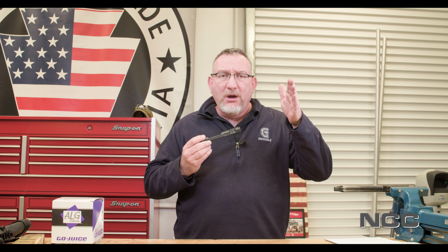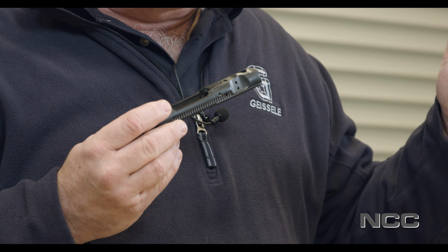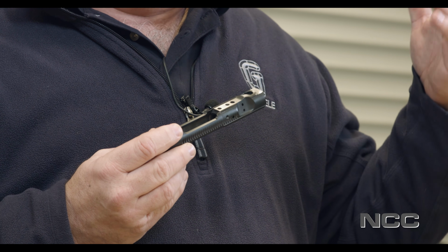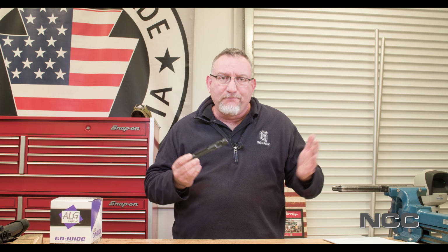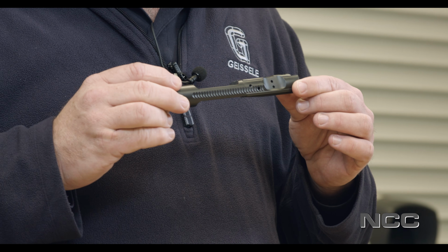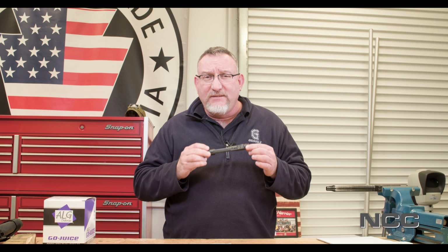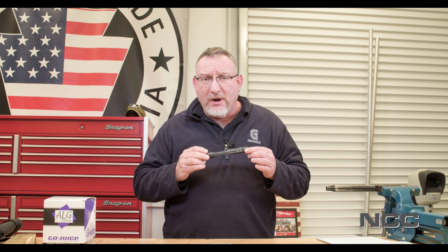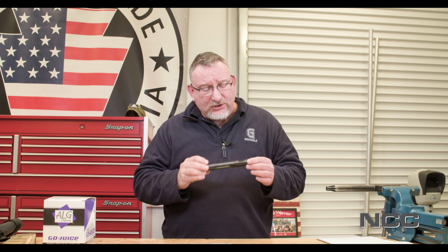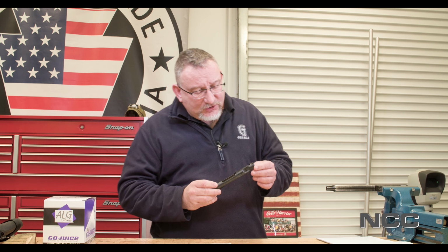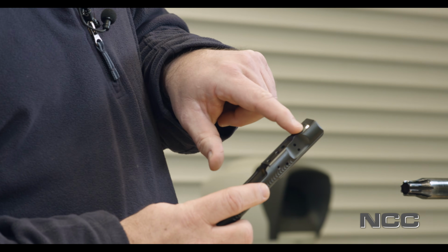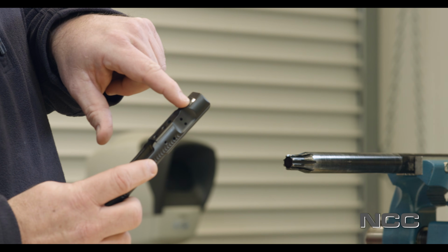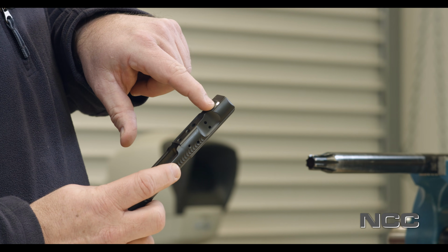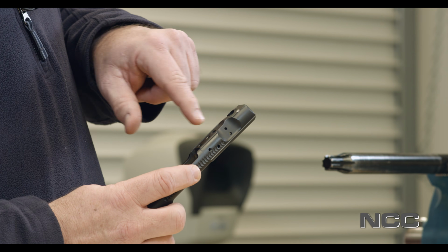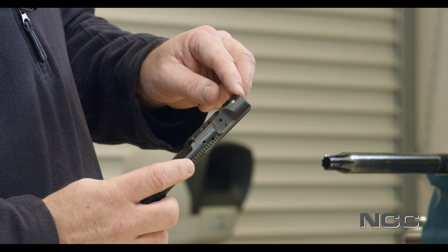So the final thing that we do in our QA process is we take sample triggers and we run them. Generally, we've had triggers that we've run to 250,000 cycles. This bolt carrier has been in our cyclic tester for 450,000 simulated rounds. And if you look at this right here, you'll notice the very edges right here, the top layer has come off the coating. You'll notice the rest of this, it's not even marked.